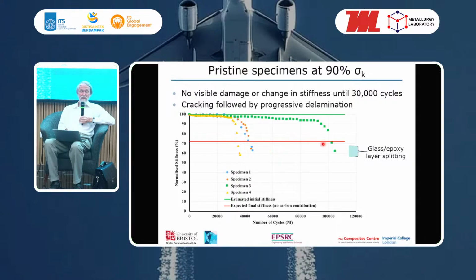This red line here is the contribution without the carbon. So if you just took the glass without the carbon, you'd expect it to be about 70% of the stiffness of the original laminate, and you can see it drops down actually a little bit below that level, because there's some splitting of the glass which also affects the load carrying response. But essentially at this point here, you're losing the contribution of the carbon.